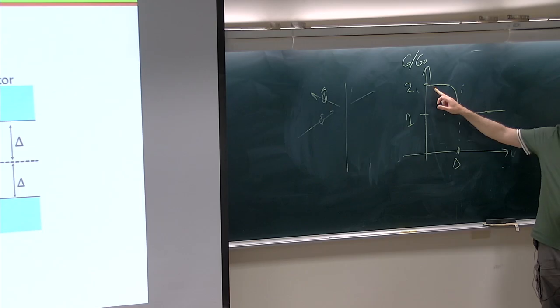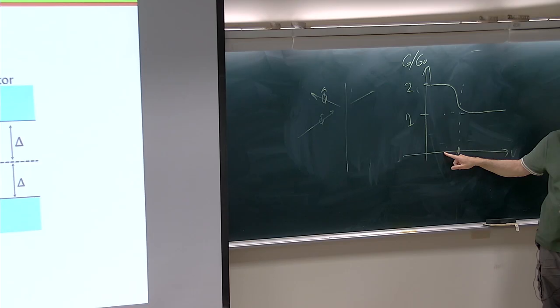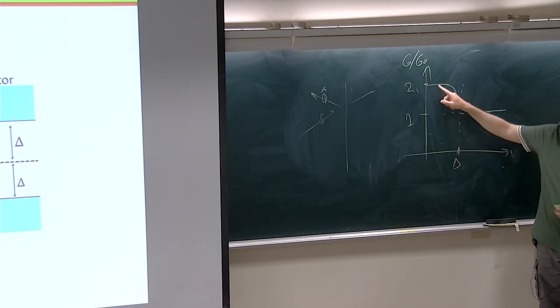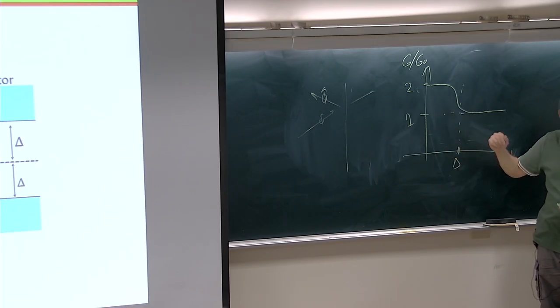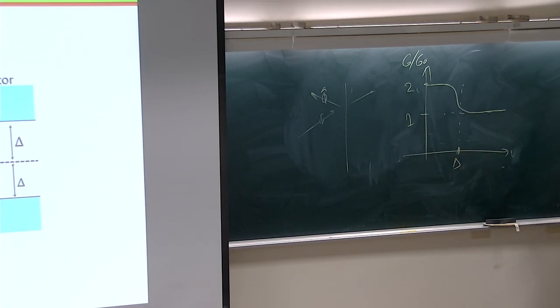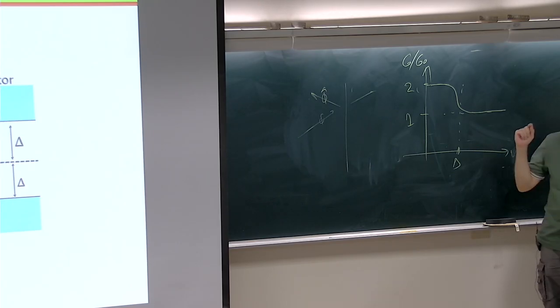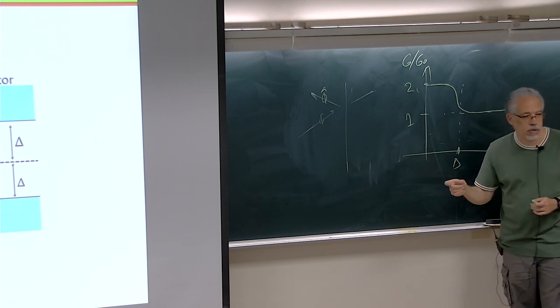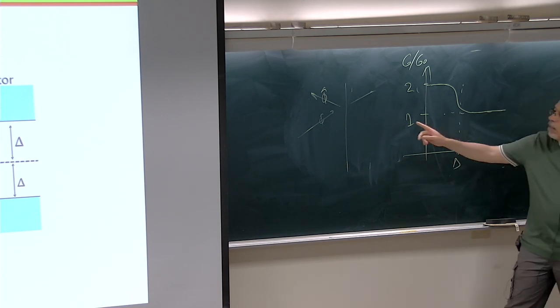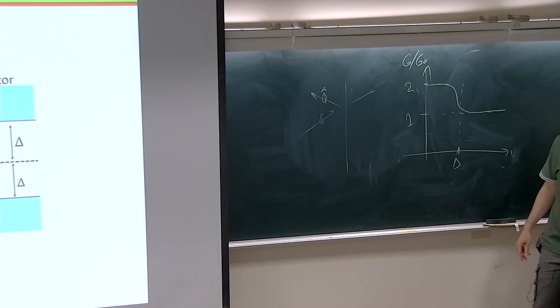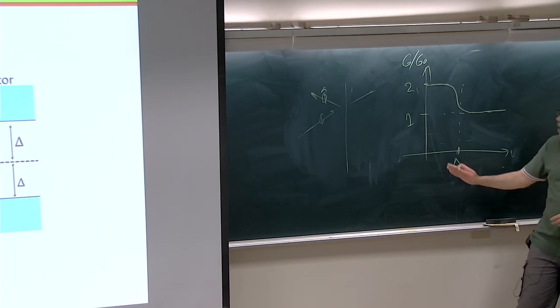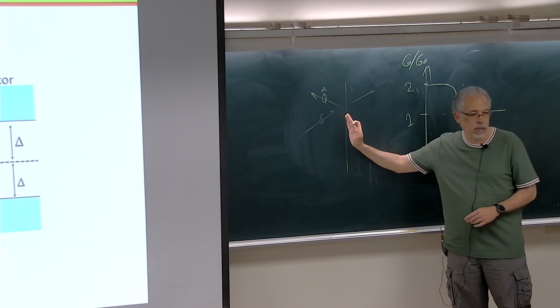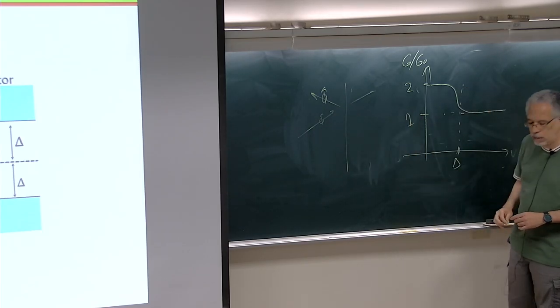If your spin polarization is large, then this starts to go down, down, down to 1 if you have 100% polarization. So when you measure how much this goes down, you can then extract the spin polarization. There is a caveat: you need these interfaces to be good, because you also have contributions from the normal reflection. So you will try to minimize this normal reflection so that you get this.